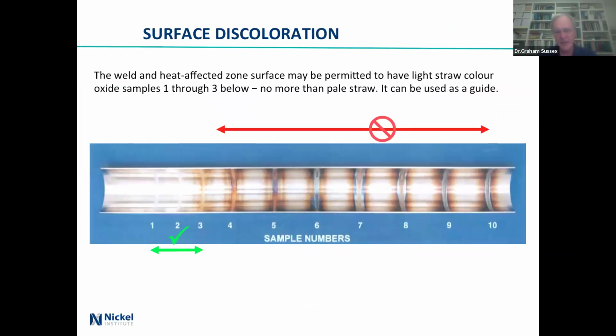This is the AWS standard. It was done for food, but it works perfectly well for ordinary corrosion resistance. And down in the green bit on the left, you get that level of heat tint corresponding at 3 to about 40 or 50 parts per million of oxygen. And they basically did it by running gas through with levels of oxygen and then did welds around the outside. Talk to the bloke who did it. No more than pale straw. Can be used as a guide.